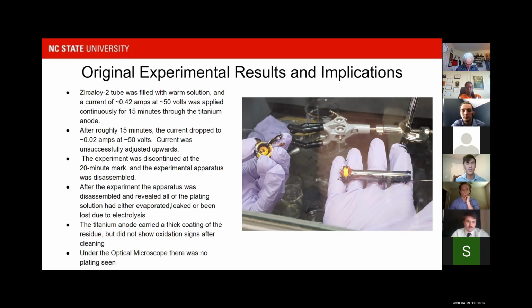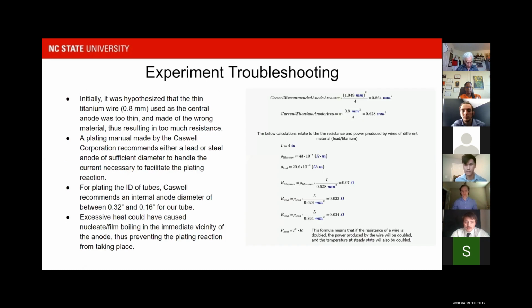We applied it to the titanium anode for about 15 minutes. After about 15 minutes, we dropped the current and then checked the inside of the tubing. After checking the inside, we realized that most of the chromic acid solution had been either evaporated, leaked, or lost due to electrolysis. The titanium anode had thick signs of residue on it, but didn't show any oxidation. Ultimately, under optical microscopy, we checked the inner tube, and it showed no signs of plating. So after our first iteration of the experiment, there was no chromium plating visible on the inner diameter of the zirconium tube.